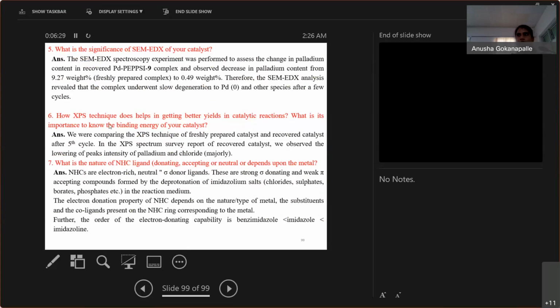spectroscopy. How does the XPS technique help in getting better yields in catalytic reactions? What is its importance, to know the binding energy of every catalyst? We compared the XPS technique of freshly prepared and recovered catalyst after the fifth cycle. In the XPS survey spectrum of the recovered catalyst, we observed a lowering of the peak intensity of palladium and chlorine. The intensity of palladium is decreased in the recovered catalyst compared to the freshly prepared catalyst.